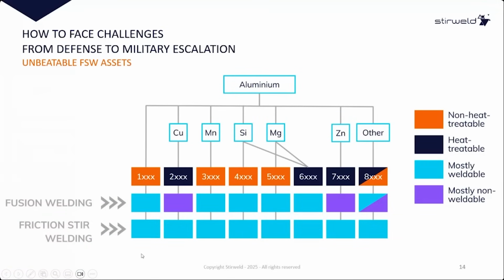Here on this drawing, we have the different aluminum families: 1, 2 series, 3, 4, 5, 6, 7, 8. With the different colors, we show whether we can weld by fusion or not. When it's purple, it's not weldable, or not all, but most of them. Generally, when you ask a welder, can you weld the 2000 or 7000 aluminum alloys, it's not possible or very, very difficult. By friction stir welding, it's possible to weld any kind of aluminum alloys. Why? Because all the defects that we meet when we weld 2000 and 7000 by TIG, MIG, laser all appear at liquid state. Friction stir welding is solid state, so we don't have these defects. It's very simple.